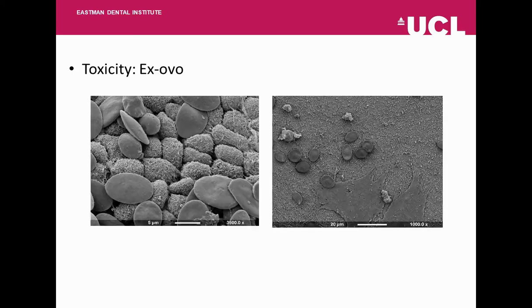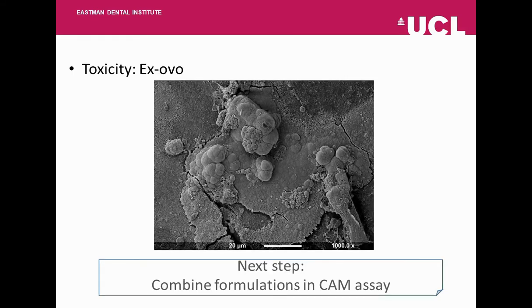For the highest level of monocalcium phosphate, at 16%, we actually noticed on the disc under the scanning electron microscope the physical characteristic parents to the hydroxyapatite, the ball-like structure, suggesting that in this environment, the discs were able to remineralize, not too different to what may happen in the body.